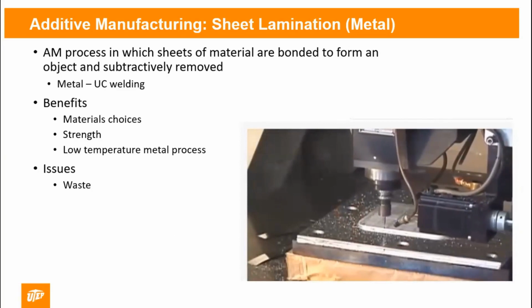There's been at least one case where they put fiber optics into this structure, and then they lay metal on top of it. And because of the very selective nature of the heating, the fiber optics survived. In 2007, I worked with Utah State University, which had one of these systems. We actually put electronics inside with a deposition system and placement of chips, without having thousands of degrees C of some high performance metal melting. It opens up a lot of possibilities. But I just don't see any of the sheet lamination approaches really being broadly adopted.